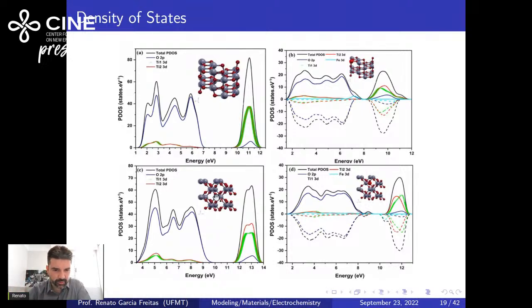In this case here for rutile, we have higher contribution of oxygen in different parts, in this way, from titanium in the conduction band. Here is the same, large contribution of oxygen in the valence band and higher contribution of titanium, and you split this part as well, the contribution of titanium from the first layer where the iron was doping, and the titanium from the second layer as well.